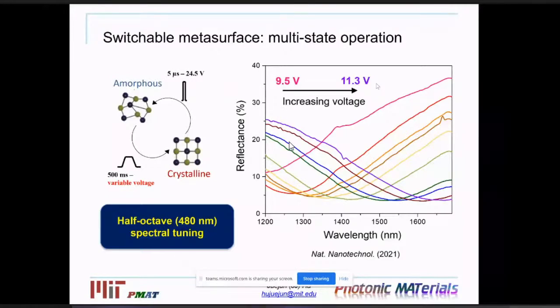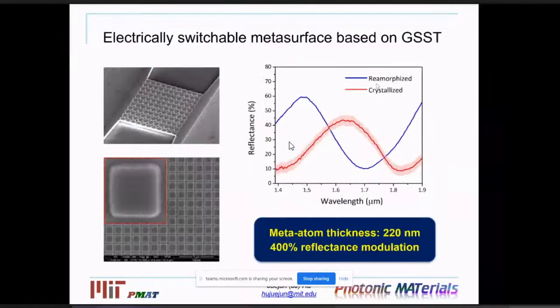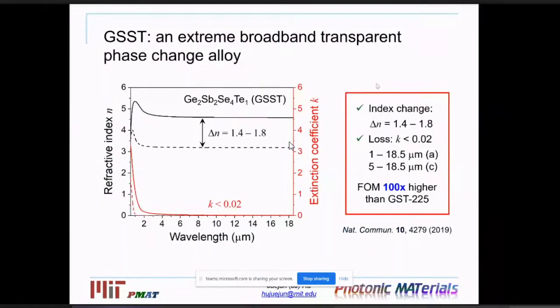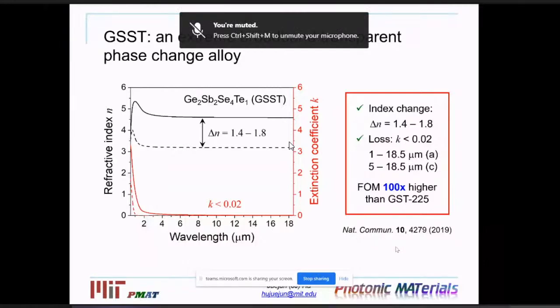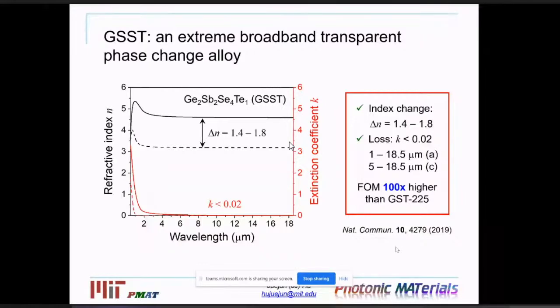Usually you anneal and then see whether it crystallizes to cubic or hexagonal. But at the device level, is there a way you can make sure it's the cubic phase or the hexagonal phase? Yes, you can do that, a few different ways. One way is to use in situ TEM. That's kind of what we did. If you read our paper about GSST, we did in situ TEM to look at the phase transformation during the heating process. We were able to see a transition: it quickly goes to cubic, and then quickly goes to hexagonal because the heating temperature was high at the time. So you can verify the structural transition in situ using that technique.